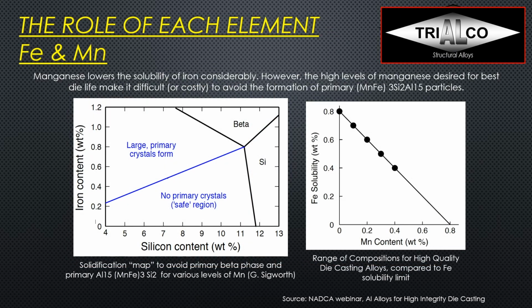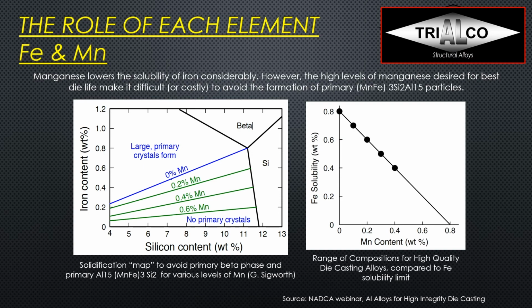So now there's a lot of interaction between iron and manganese, and we have to watch out when we add those two elements. We already know a sludge factor, so manganese goes in with a factor 2 of iron, so we have to be careful how much manganese we can add. But then there's another factor, and that is whether we create large primary crystals, and they would also be bad. So we look at iron content and we look at silicon content. We see here on the left side this blue curve, it's going up. So the more silicon I have in there, the more iron content I can tolerate without forming these large primary crystals. But this blue line actually goes down the more manganese I am adding, and therefore if, for example, I am adding 0.6% manganese and I am at, let's say, 10% silicon content, I can go over to the left and I see, well, I really should be well below the 0.2 iron content.